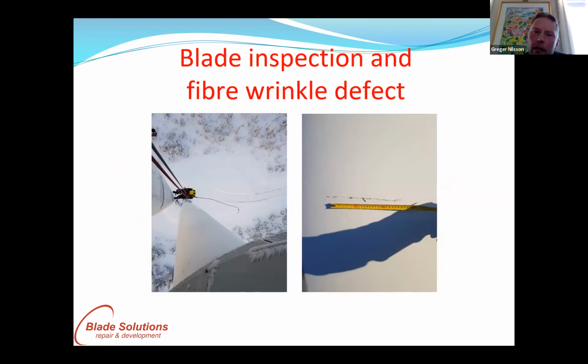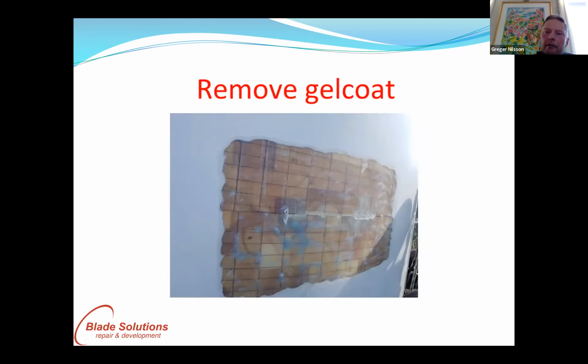This technique is developed for repairing fiber wrinkle defects. It is quite a common defect when you make a blade that you get some fiber wrinkles and you don't find it in the factory. So after some years, you will find a crack. In this case, we go down and find this crack. If we remove the gel coat, we can see that we have a crack here, and we have some delaminations. It's quite important to repair this as soon as possible before we get crack growth.